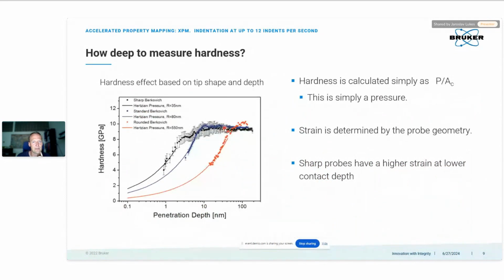If you have a dull probe, you produce the plastic deformation at a later stage. So you have to push the tip deeper into the material to produce enough plastic deformation to measure the intrinsic property of hardness, or the intrinsic hardness of your phase. So these are 3 different examples of 3 different tips. The first tip is quite sharp. It's a very sharp tip. The radius at the end is 35 nanometers. The second one is 80 nanometers. The other one is half a micron.